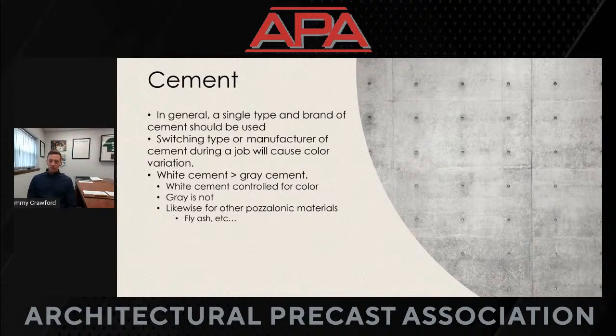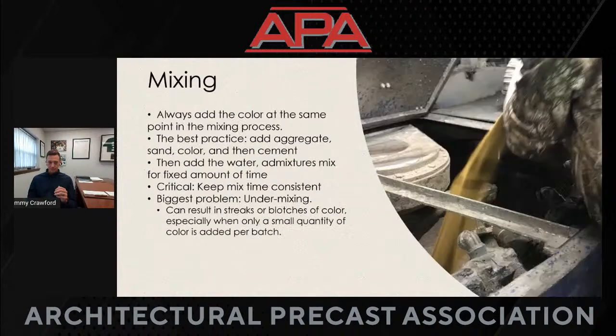Cement. In general, we strongly advise using a single type and brand of cement. If you are going to switch between jobs, a change in cement manufacturer will cause color variation during a job. I'm probably preaching to the choir in this particular presentation, but white cement is always more closely color controlled than gray cement. Some cement suppliers, I'm not exactly sure what their QC process is for gray. I know it's reliably controlled for white. Other pozzolanic materials such as fly ash or slag are kind of a mixed bag. Some are going to be more closely color controlled. Some are going to be less color controlled.